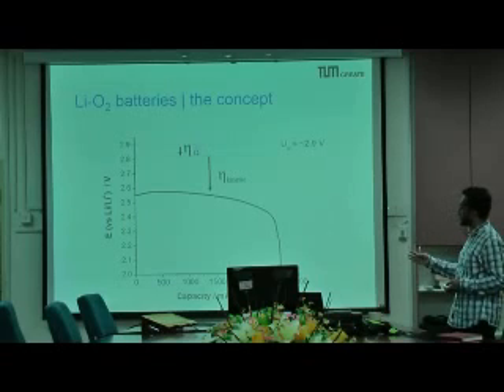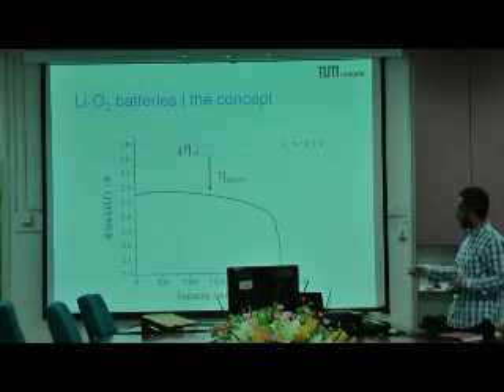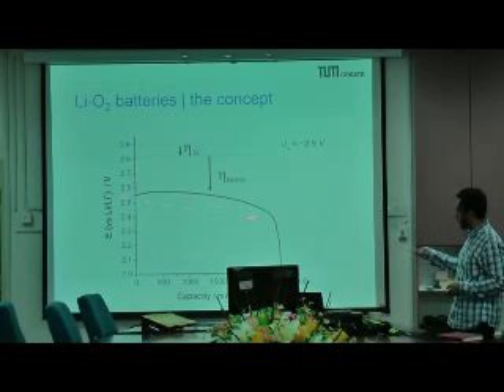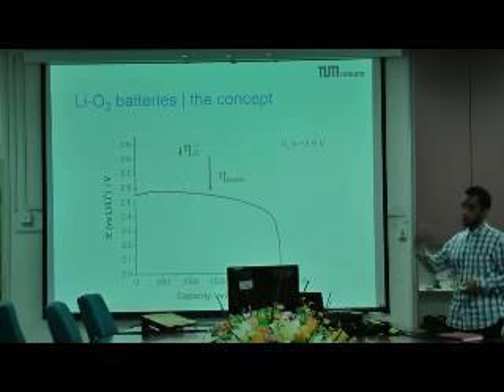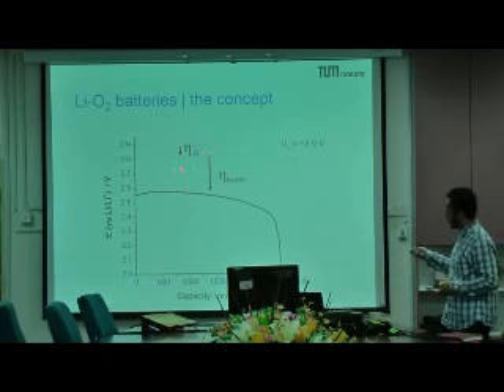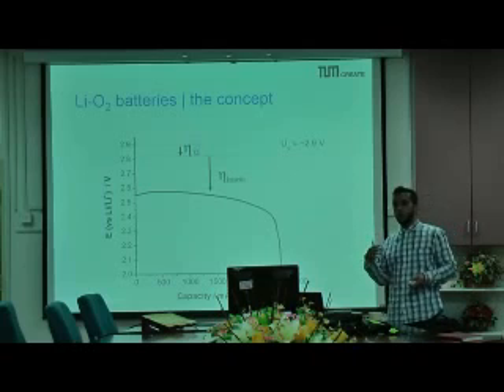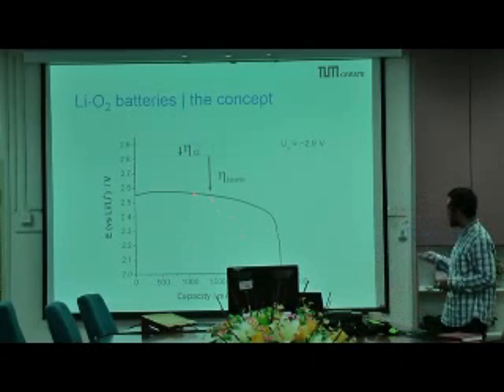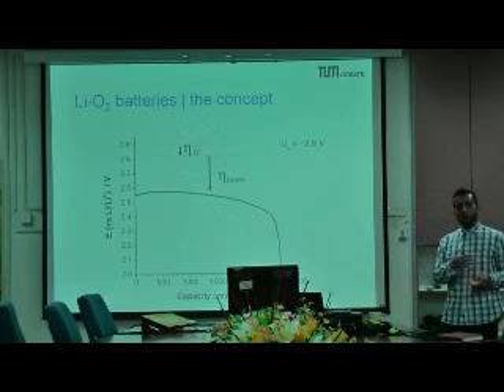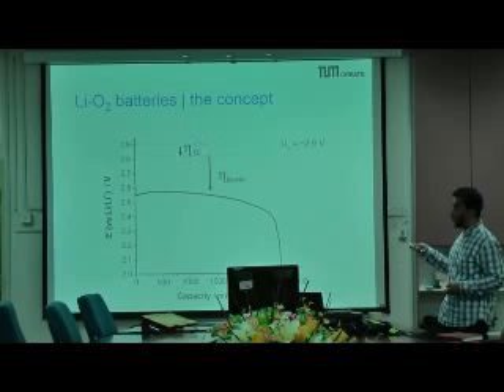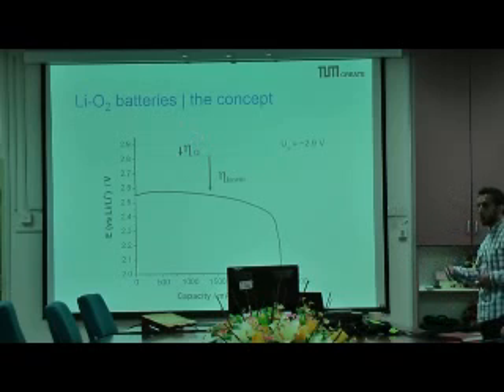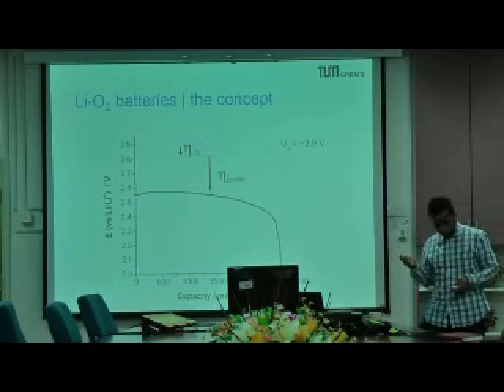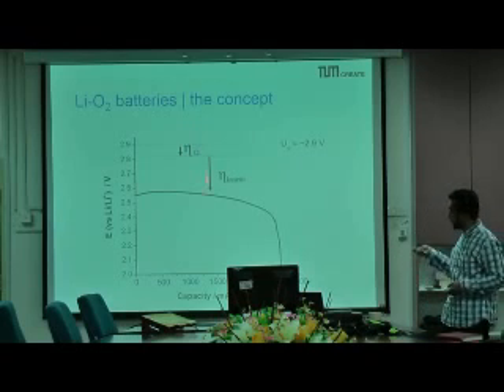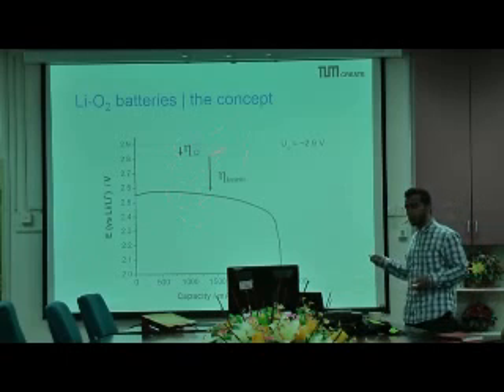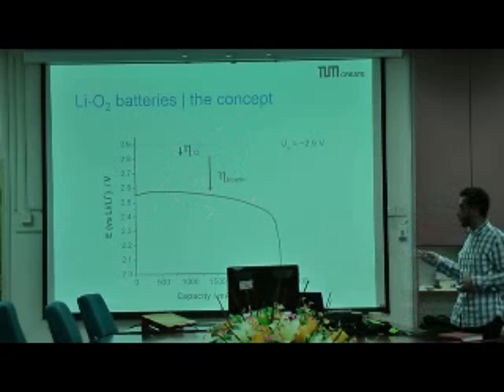A typical discharge curve, when you apply a constant current from a battery, is the following. You have a roughly constant voltage, meaning that at this stage the potential is constant while electrons are being drained out of the system, reducing oxygen. And you have two potential losses, meaning barriers that you have to overcome to make this work. One is the potential coming from the electrolyte. If the electrolyte is conductive, then you have a very low IR drop. If the electrolyte is poorly conducting, either because there are not many ions around or because of high viscosity, then you get a large IR drop. The second is the intrinsic property of the cathode material, the overpotential of the kinetics.